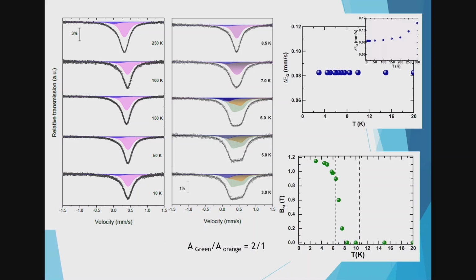Actually, you can fit if you increase the width of the lines and put hyperfine field, you fit. If you increase the quadrupole splitting, as I showed you before, when it seems to have an anomaly, we feel that if you increase the quadrupole, you fit. Anyhow, you have to put the angle in the fit. It's very important to put the angle in the fit, otherwise it doesn't fit.